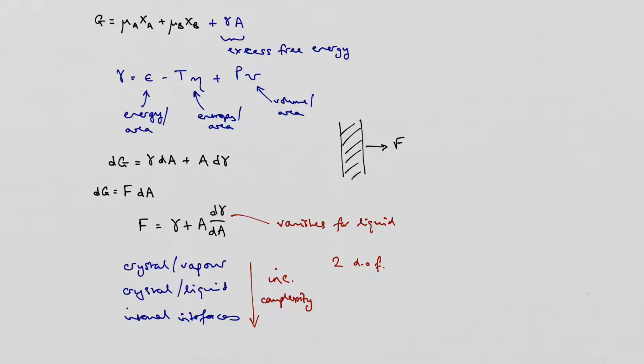With the second one, there are 3, because I can take a direction in the first crystal and tell you what I need to do to rotate that into the equivalent direction in the second crystal. So that's 2 degrees of freedom. And then I can rotate it around that axis. Does that make sense? So there are 3 degrees of freedom essentially defining the relative orientation of 2 crystals.